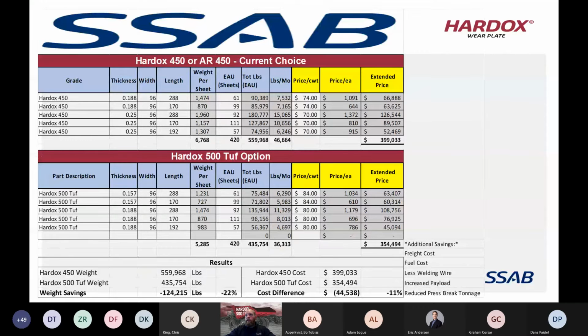This is a brief cost comparison based on going from Hardox 450 at 3/16 and 1/4 inch to a Hardox 500 Tuf option that is 4 millimeter, or 3/16 of an inch. The results we could see were a weight savings of around 22%, but also a cost difference in the steel. Your steel costs are reduced by about 11% because we were able to reduce the thickness of the steel. You can keep the same relative service life of your equipment with a lighter option and have a better cost structure.